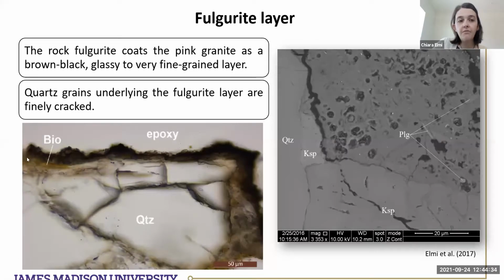The rock fulgurite was a black, glassy coating in texture above the rock, and you see that the quartz, which is generally very smooth under the microscope, has these fine cracks close to this black coating, evidence that there was a shock. And at the electron microscope, you see some fragments of residual minerals that came from the rock when the lightning struck the rock.